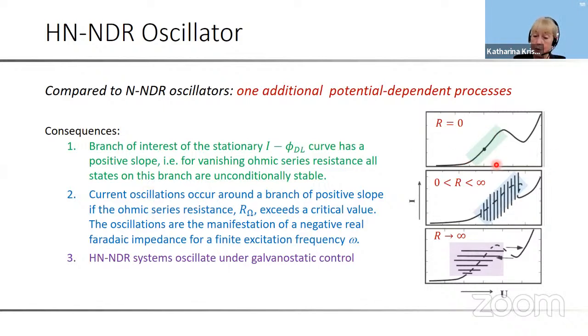The current oscillations that you observe under potentiostatic conditions occur from some critical ohmic resistance on. So as soon as electrolyte resistance, or the cell resistance, exceeds a critical value. And the oscillations, in fact, are the manifestation of a negative real Faradaic impedance for a finite excitation frequency omega. And how this comes about, I will show in the next slide. Important is to note that when you have such a hidden N-NDR oscillator, the system oscillates also under galvanostatic conditions, which is not possible for N-NDR oscillators.